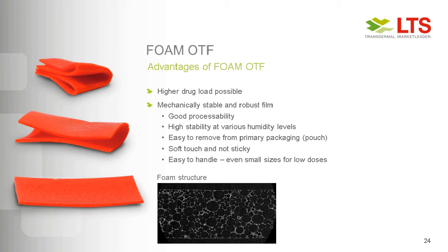On the bottom, you see a cross section of the foam structure, including a lot of bubbles in there, which increase the surface area and which then allows a much faster disintegration time.